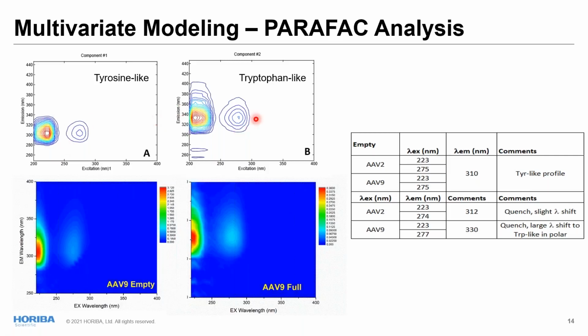We see a tyrosine-like component and a tryptophan-like component. Actually, one of the important differences between PARAFAC and PCA is that PARAFAC is, even though it's conceptually similar to a PCA, the component scores and loadings that result typically present actual true sample components. So that's a little different from PCA, where it's more of a statistical variance analysis than deriving pure components. So this helps us in trying to understand what's going on here. So again, we have a tyrosine-like component and a tryptophan-like component.